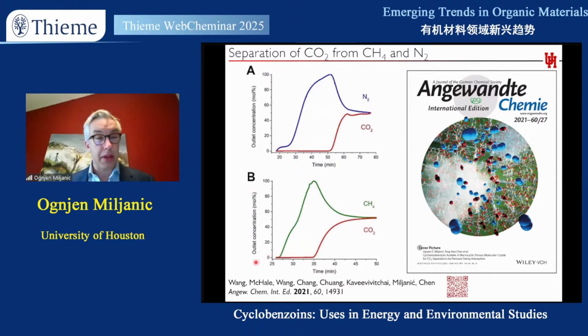And so these are experiments where we pass a stream of a 50-50 mixture of carbon dioxide and methane or nitrogen through our crystals, and then we monitor what happens. So the gas travels through the column, and then after that time, what starts coming out is pure methane, and this pure methane flows unimpeded for the first 10 minutes. And at that point, the column is saturated with our gas mixture, and so then it slowly reverts back to the 50-50 mixture. And something similar is seen in the binding of nitrogen. This makes sense because methane is not linear, so it's not included in the pores, while nitrogen is linear, interacts with them very well, so it's kind of flushed out very quickly.